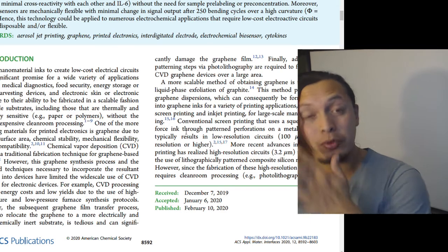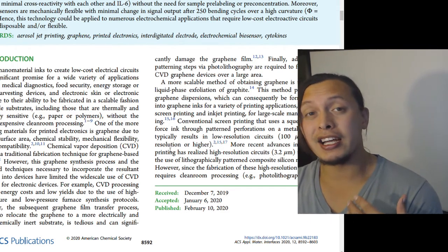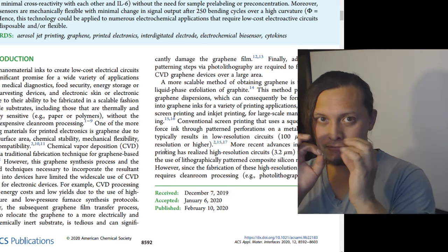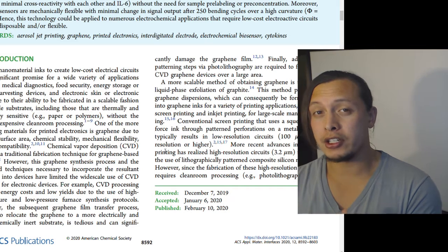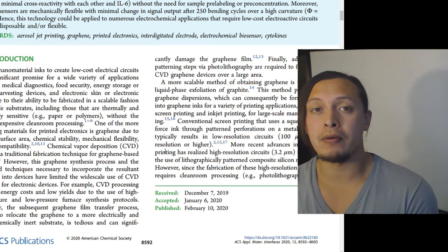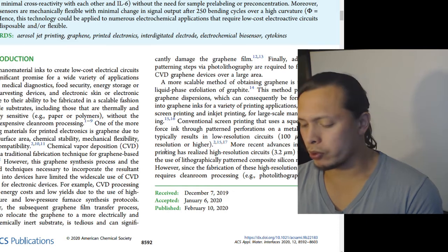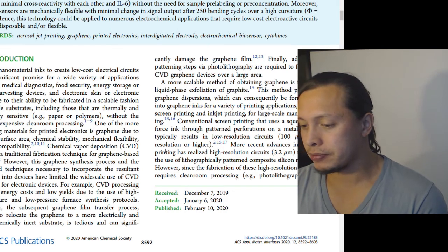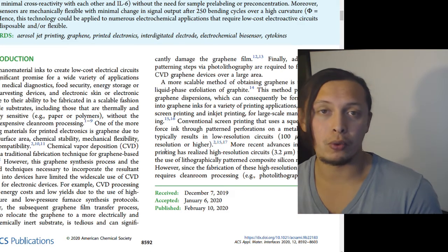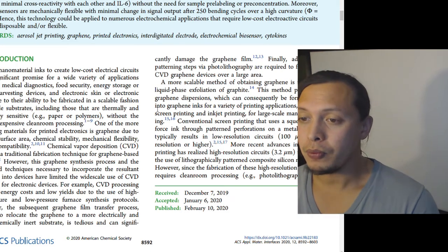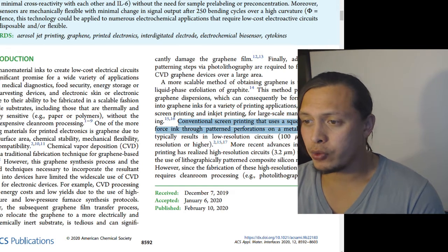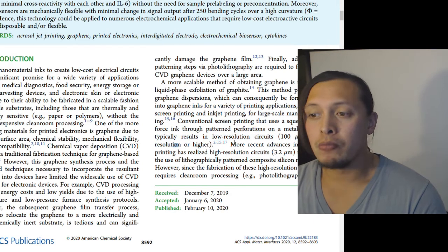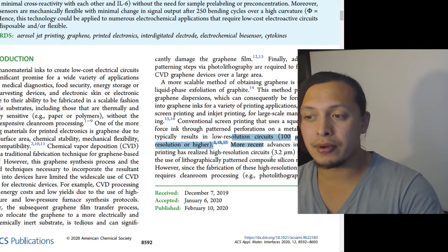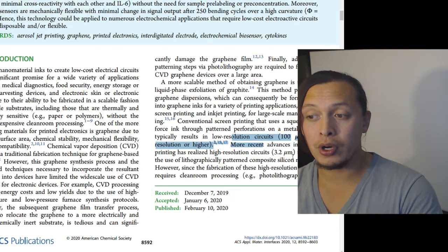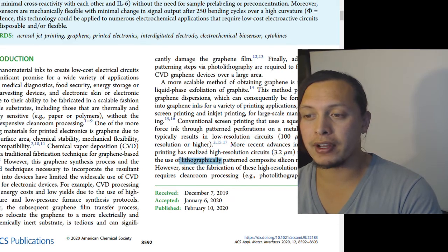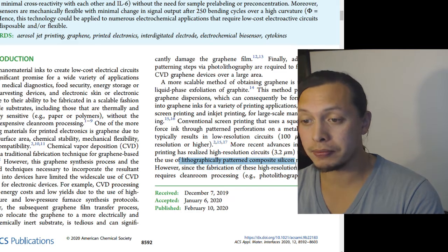But with this conventional screen printing for graphene-based inks, it's very low resolution. You can't get the minute details that you need to have, say, high surface area and more specificity, and what would the word be? Not selectivity, but sensitivity to whatever material or molecule you're trying to detect. Anyways, conventional screen printing uses a squeegee, and more recent advances in screen printing have realized high resolution circuits, 3.2 micrometers, through the use of lithographically patterned composite silicone molds.